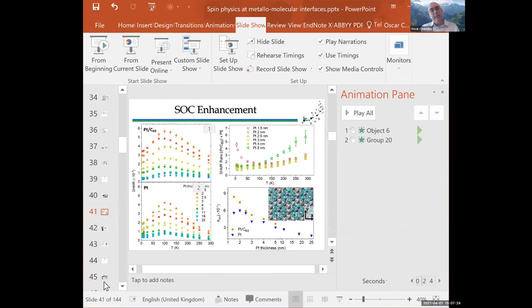Indeed. I mean, still work to be done. But for us, the fact that both the SHMR and the AMR, importantly, in both platinum and tantalum increase when you put C60 on them, independently of whether the resistivity is increased or reduced. So for both systems, these enhance. That means there is an enhancement of the spin orbit coupling. We cannot say the spin orbit coupling is different, but the effect of the spin orbit coupling is enhanced. So how the spins are split in direction according to their orientation depends on this.